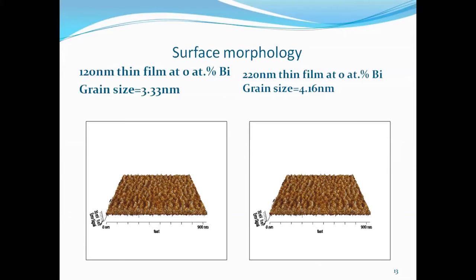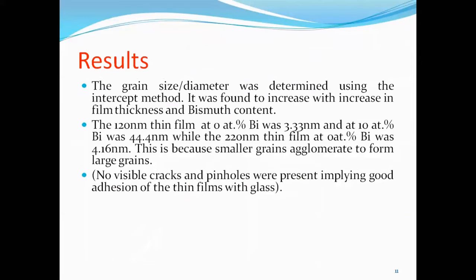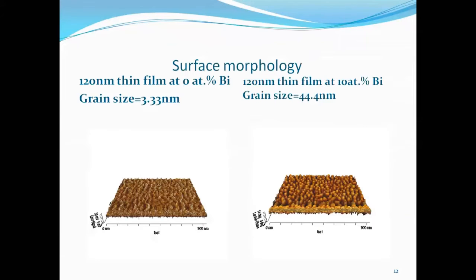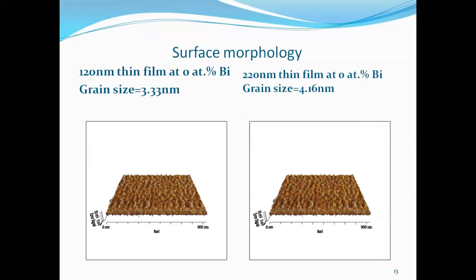So this simply tells us that grain size increases with increase in film thickness, and this is because, when you use a thicker film, the smaller grains agglomerate to form larger grains. Now, if you go back to our pictures, you'll see that there are no visible pinholes or cracks. So this means that it can make a good film for solar cells.